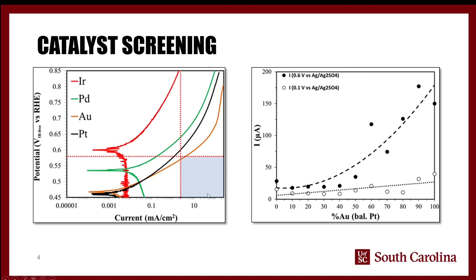We also wanted to consider whether or not some kind of combination, given that gold and platinum were very similar in terms of the onset potential, we considered whether a mixed metal catalyst might be worth looking at. But as you can see here, regardless of the voltage that we used, we looked at both 0.1 and 0.6 volts versus a silver-silver sulfate reference electrode. In both cases, pure gold had the highest activity. So again, we looked basically at pure platinum and pure gold. Did not mess with any of the mixed metal, bimetallic alloys or anything like that.